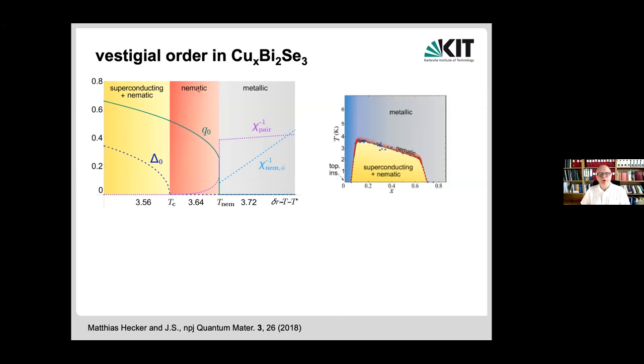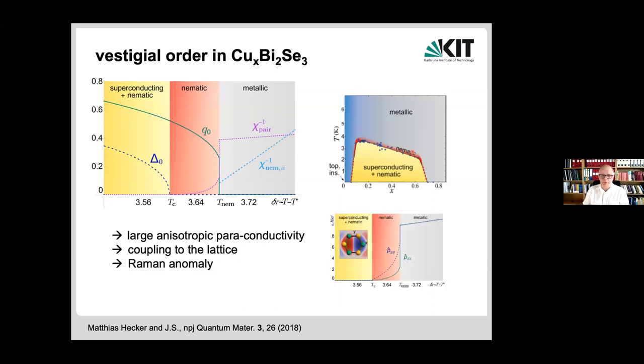Once you enter that phase, superconducting fluctuations will be vastly increased because the system now is much less frustrated, and you would also expect that there will be some lattice softening going on, even though this is a first order transition. Ultimately, there will be no elastic constant going to zero. So we expect that there's a region above the superconducting phase transition where you expect a nematic phase that is not superconducting in its own right.